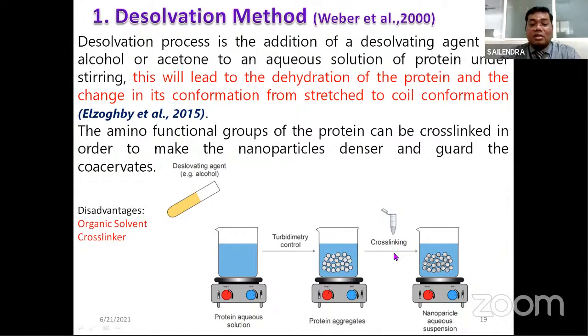Now you will be using a cross-linker. This cross-linker will be glutaraldehyde, and whenever you add glutaraldehyde, all these nanoparticles are going to gel to each other and they will form a cross-link with each other. And that cross-link is immediately done in alkaline solution. Now, always remember, glutaraldehyde forms denser cross-links in an alkaline medium compared to an acidic medium.